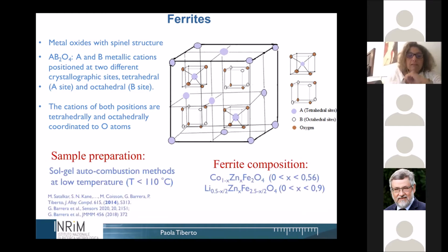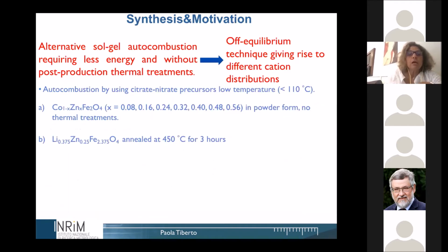We have prepared these samples by sol-gel autocombustion. Here are the compositions. Why have we used this? Because it's an off-equilibrium technique, and this can give different cation distributions and hopefully different magnetic properties. The cobalt zinc ferrites do not need any further treatment, while the lithium ferrites do; they have to be treated at this temperature.